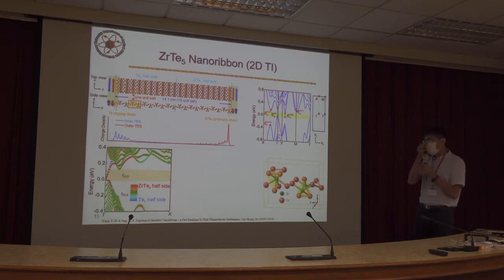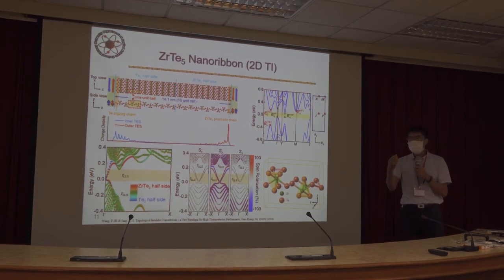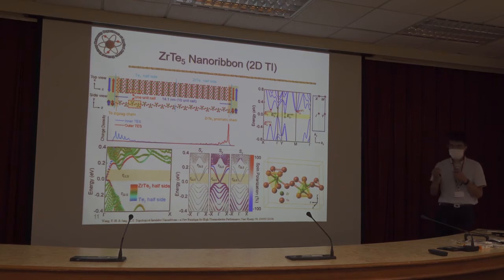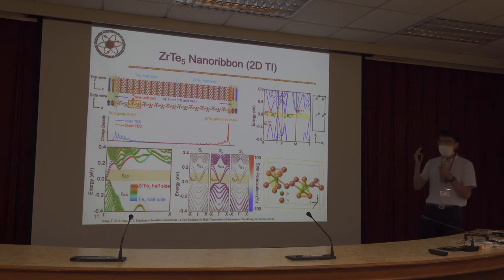So there is almost no interaction between the topological edge states at different edges. Besides, at the same edge, the topological edge states moving forward and backward have opposite spin polarization. So backward elastic scattering is also forbidden. As a result, the in-gap topological edge state should have a large relaxation time, much larger than the other states which are outside the gap. So we call the intact topological edge state the long lifetime state, and the other states the short lifetime state.